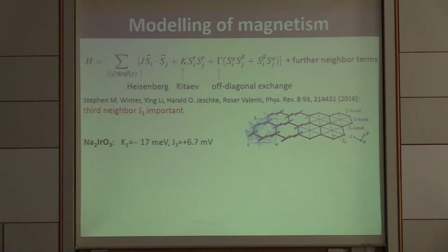Now, to really model the ordered ground states and the excitations requires involving, in addition to the Kitaev-type interaction, several other terms. Not only the isotropic Heisenberg exchange is important, but also this off-diagonal exchange, which I mentioned, which mixes, for instance, along the Z bonds, also the X and Y components of neighboring spins. And then it was found that not only nearest neighbor interactions are important, but in principle all these three terms could also appear for second and third neighbors. So there is a large variety of parameters one could play with. But it was found that in the real materials, in most cases, only a few of them are important.